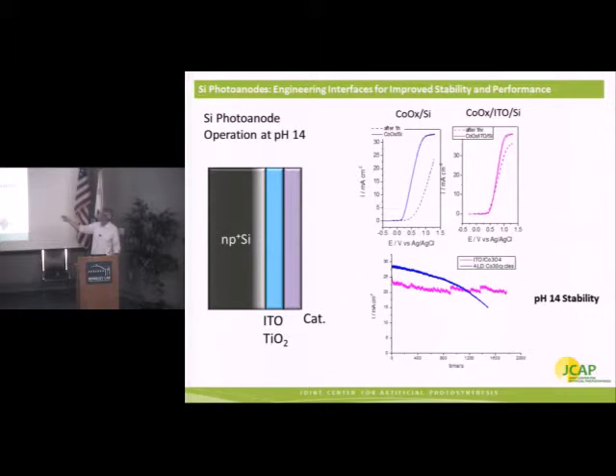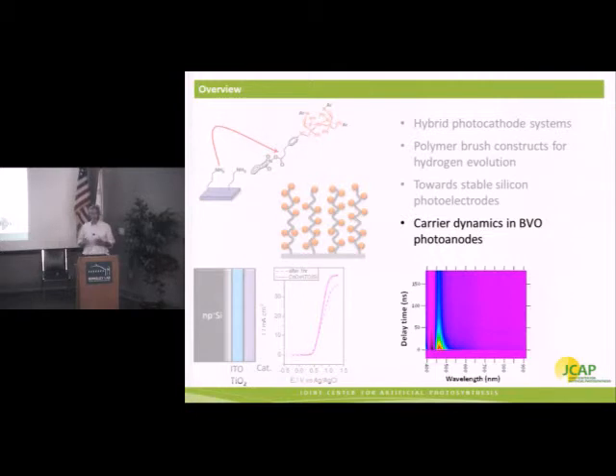And here we see similar curves where the cobalt oxide directly on silicon shows promising performance initially, but it degrades over time. However, if we introduce this interfacial ITO layer, we see that, now this testing was out to an hour, but it's quite stable again. In this case, we monitor the photocurrent as a function of time for cobalt oxide on these two types of surfaces. And we see with the introduction of the ITO layer, we do have quite stable operation. Some of these jumps here are likely associated with bubble formation on the surface of the electrode. Okay, so that was a demonstration of a stable photoanode based on silicon.